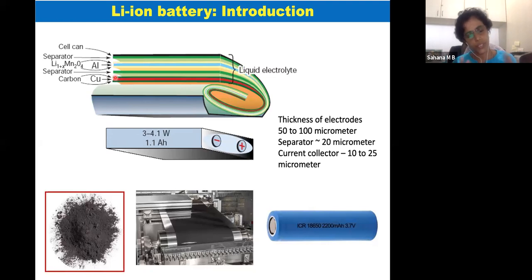Now, for a voltage to develop, they need to be separated physically. That is this line here, the green one is a separator. And now these are wound together. The thickness of the electrode on each side can be around 50 to 100 micrometer, whereas a separator is around 20 micrometer. Current collector varies from 10 to 25 micrometer. These are wound together. We call it a jelly roll, and there are many round sectors of it. So this is the inside of the cell.